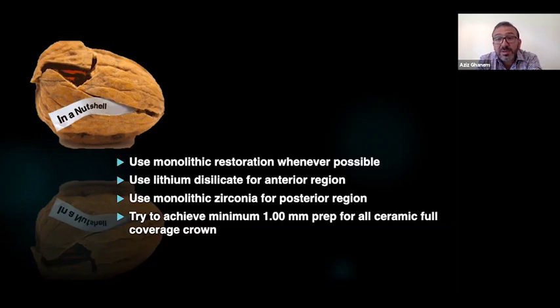But these are all tested at a thickness of 1 millimeter or 1.2 millimeter, according to the ISO standard for dental ceramics. If you are using a lesser thickness, for example 0.8 or 0.6, that's definitely going to affect the mechanical properties of this material, and it is most likely going to chip at the margin, which can cause you trouble, and then you will need to restore that and replace it.